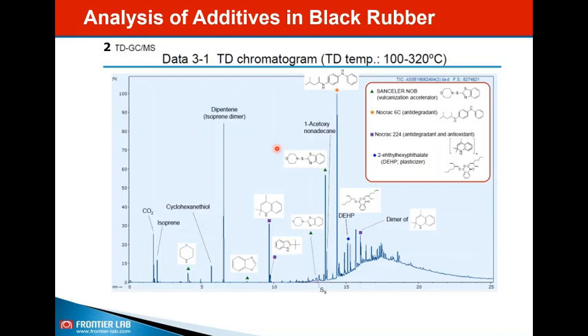That means you are basically heating the sample at a desired ramp rate from a starting temperature like 50 or 100 to 320 degrees. Later on you start the GC run for separation of these compounds. So in the standard way of analysis, people are mostly using PYGCMS for analysis of additives and polymers. Now we are going to talk about the recent developments that are helping to expand the capability of pyrolysis GCMS application.